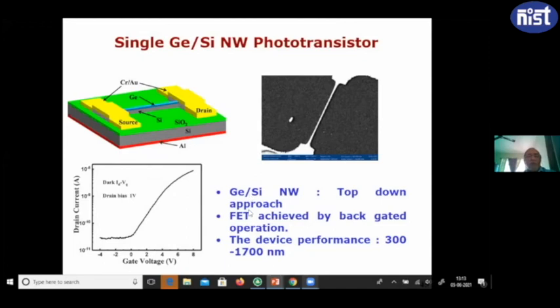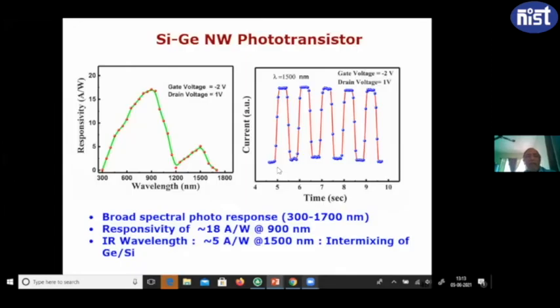So this is the last work that we have done on using a germanium nanowire, again a single nanowire. As I told you, germanium is very, very important in the fiber optic communication wavelength. The optical communication wavelength is 1500 nanometer or so. So if I take germanium on silicon, we get very, very good responsivity, firstly in the silicon wavelength range, and this is the germanium wavelength range. And as you see, you get very good responsivity. So this is a kind of two-channel detector, one channel in the near-infrared range and one channel in the fiber optic wavelength range. And you can really detect very, very low optical power with this.